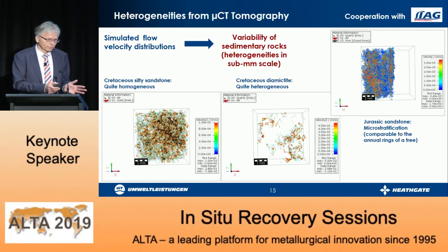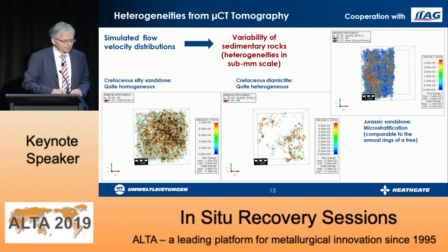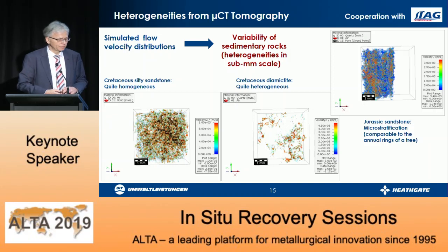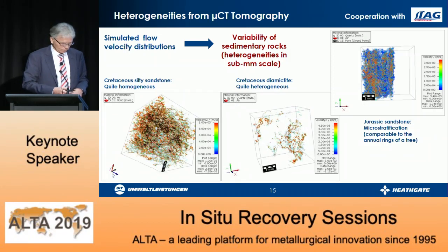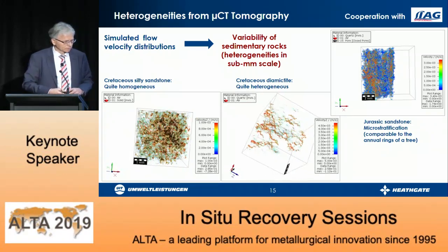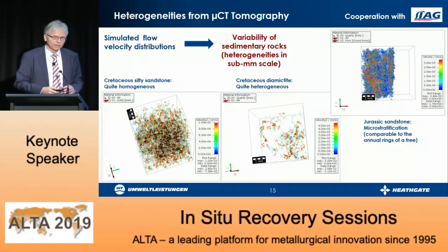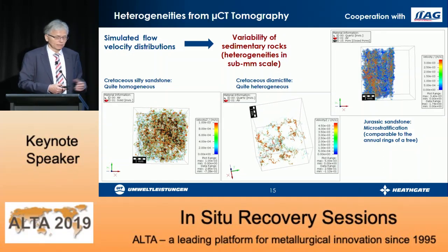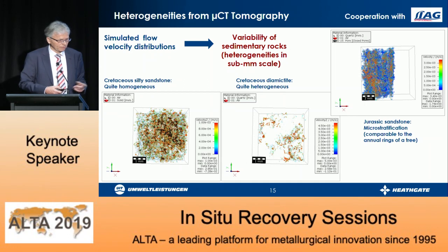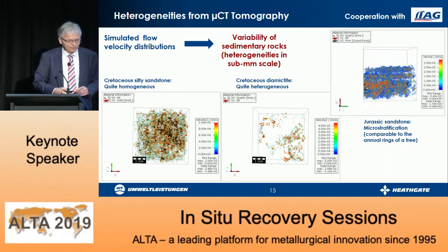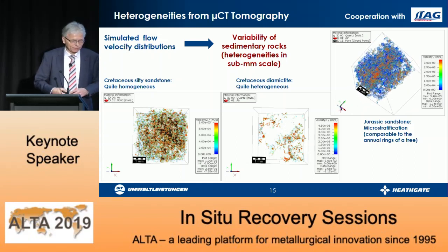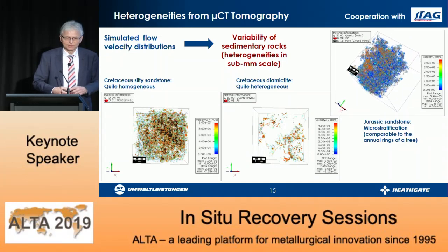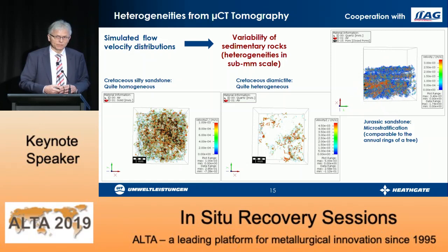Next, just to focus on what we can learn from some core studies, and here I refer to the importance of heterogeneities in in situ recovery based on studies of microcomputer tomography to simulate the fluid flow. There is one example for a Cretaceous silty sandstone, very homogeneous. There, the fluid velocity distribution is accordingly very homogeneous. Then we have a Cretaceous diamictite with quite heterogeneous conditions. And last but not least, a Jurassic sandstone, where you can see the microstratification that is comparable to the annual rings of a tree. And this points to the effect of anisotropy of the permeability in the underground.